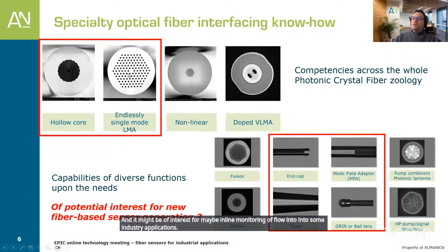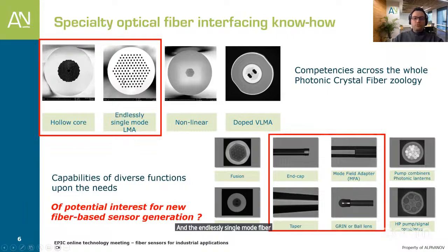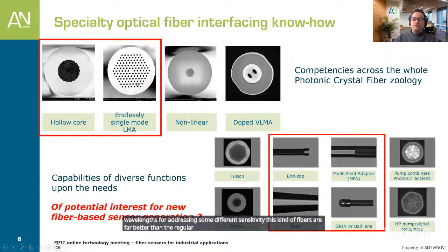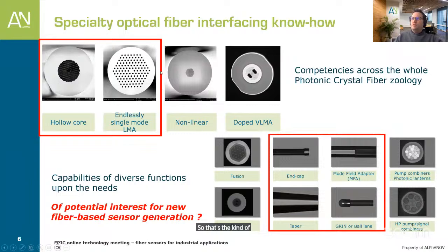And the good point of the endlessly single mode fiber is the capability to guide light over a broad spectrum, still in a monomode fashion, meaning that, for instance, this kind of fiber can guide light from 500 nanometers up to 1.7 micron and 1.8 micron. So if you want to make a sensor which would require different wavelengths for addressing different sensitivities, these kinds of fibers are far better than the regular ones, which have a single mode bandwidth of roughly 200 nanometers. So that's the kind of know-how in terms of interfacing we could propose.